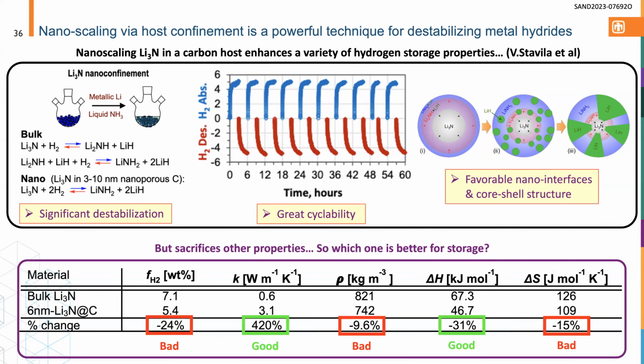Okay, so what's the drawback? Unfortunately, when you do this nanoscaling, you improve a lot of properties that are really important, but you also hurt a lot of properties that are important. So these 5 properties here, the hydrogen weight percent, the thermal conductivity, the density, and the enthalpy and entropy of hydriding are the 5 key properties you need to know to be able to size a hydrogen storage tank, for example, for a light-duty vehicle or a heavy-duty vehicle.